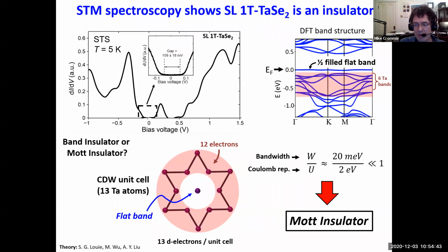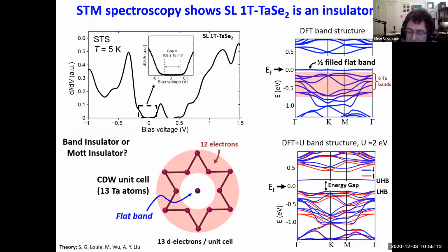We would like to understand it better, but a problem that we have is that there is no accepted theory for performing ab initio calculations on a Mott insulator. So in order to get some sense of the electronic structure of this material, we decided to make a very rough approximation, which other groups have done as well, to give us a sense of the physics. We decided to do DFT plus U in order to model this material. That's only a very rough approximation, but we did it anyway to help us out.